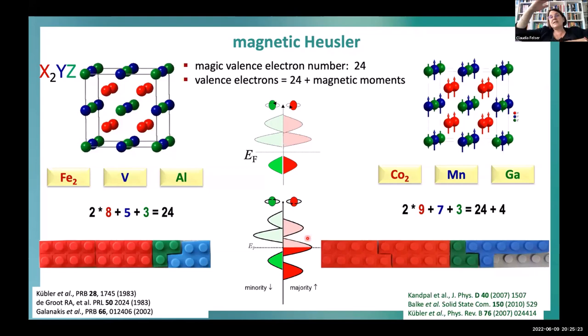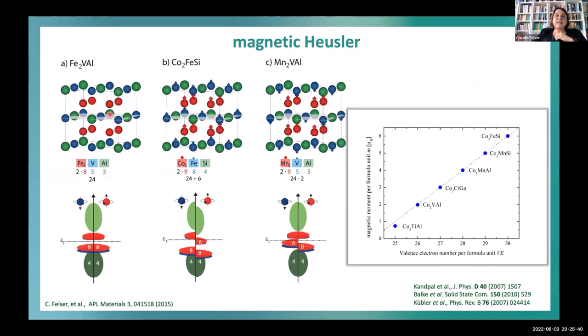exchange splitting between the red spins and the green spins increases with the number of valence electrons, because I have to fill more and more spin electrons into the red side. So we get a bigger and larger spin splitting. So this electron counting game you can play for quite a few Heusler compounds.